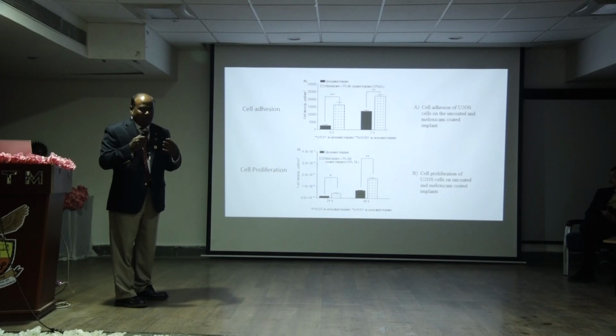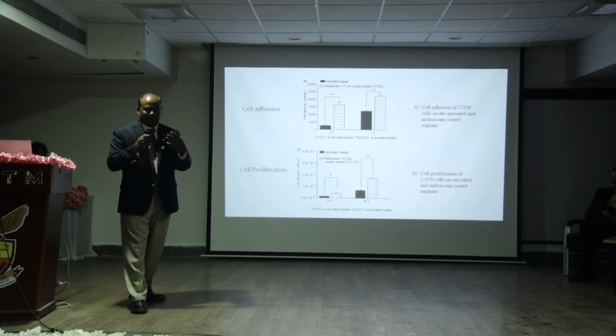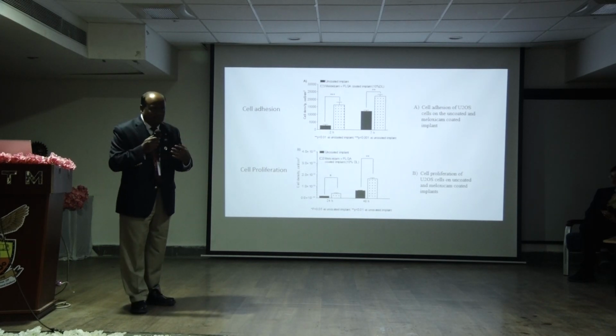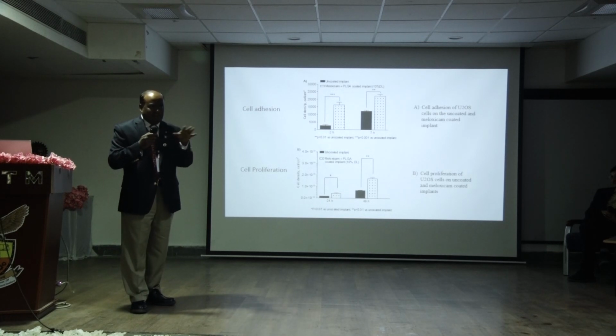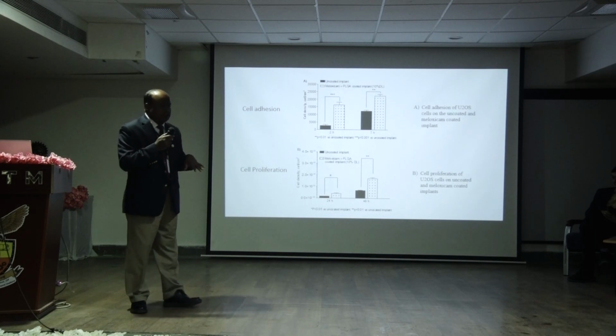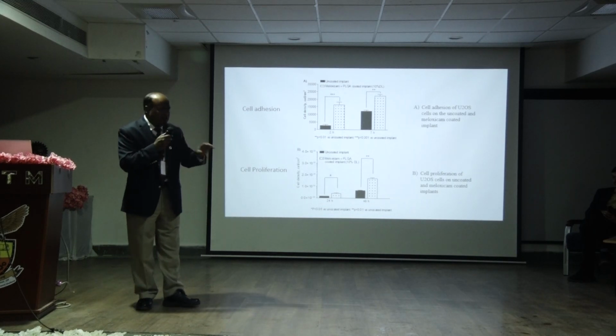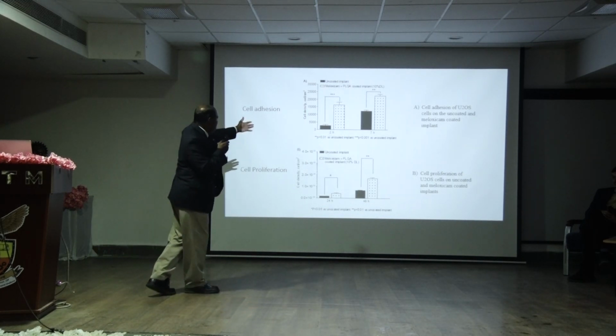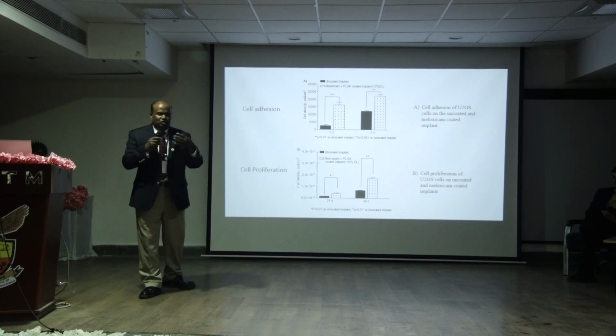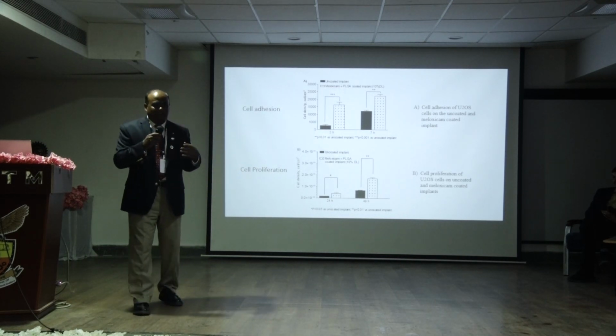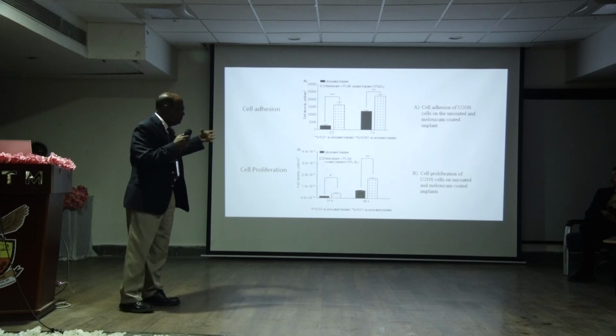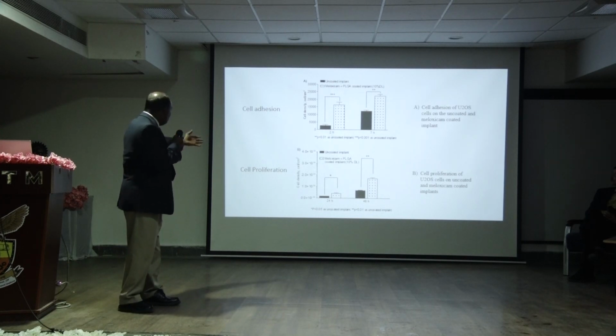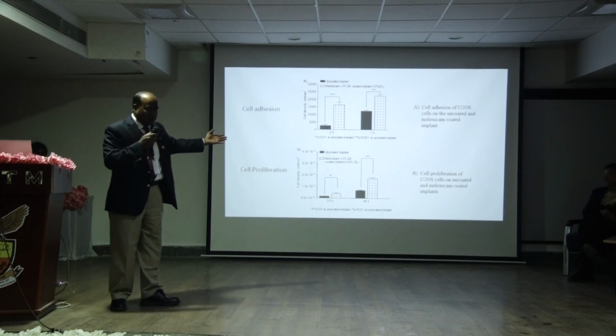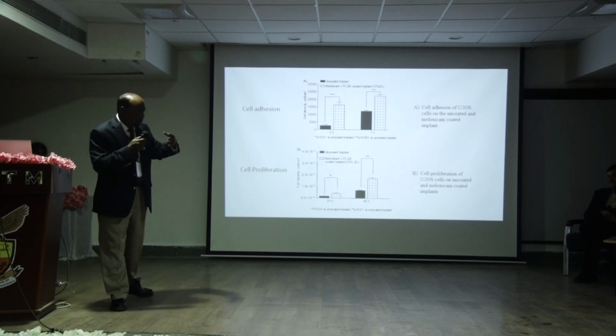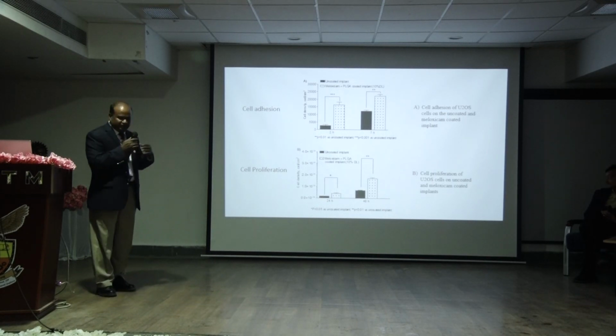by. Actually, we got an unexpected good result here. We expected at least a similar non-inferior cell adhesion compared to the uncoated implant, but to our surprise, we see that the polymer coating enormously promoted the cell adhesion, which is highly desirable. Cell adhesion is good and cell proliferation is good with the polymer deposited implant compared to uncoated implant.